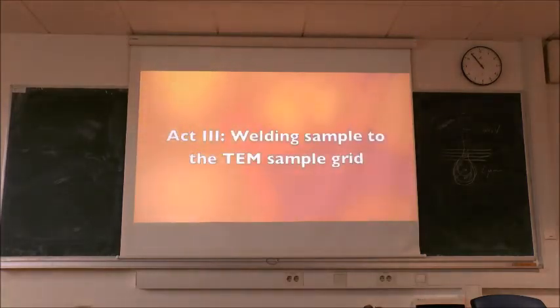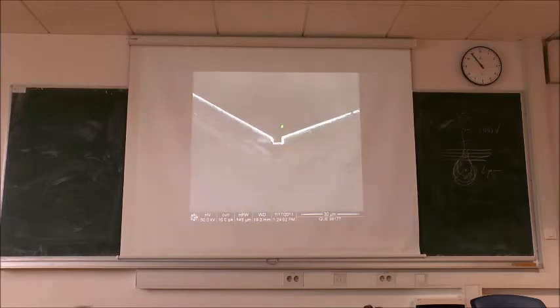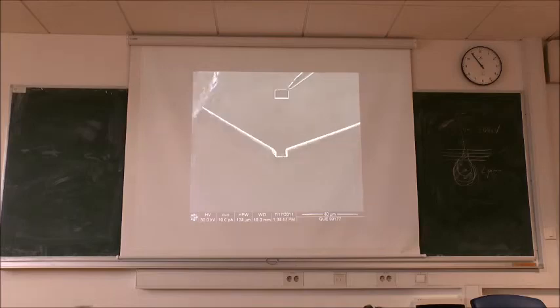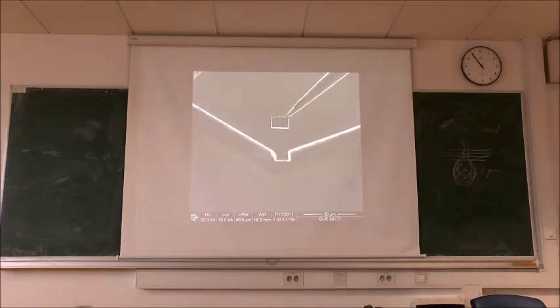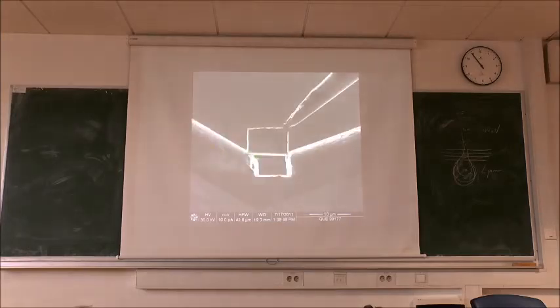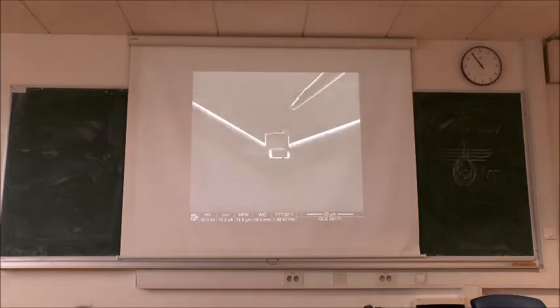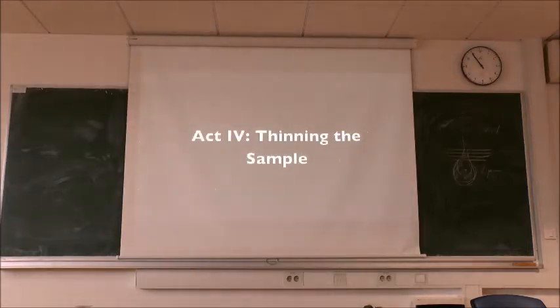Okay, and then of course you have to fix this lamella somewhere. You have some special sample holders. Fix it inside. Again, the next step is very crucial, to put this lamella here. And here, you see, this big tube is the gas injection system, where you will put again some small part of platinum. Here you cut, and you have the lamella fixed on the TEM sample holder. Of course, this lamella is still very thick and with a very large amount of amorphous material.